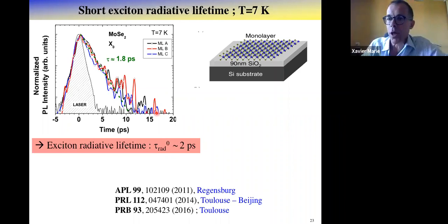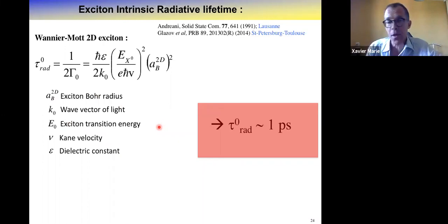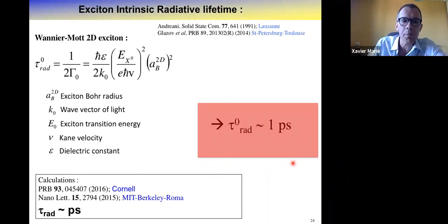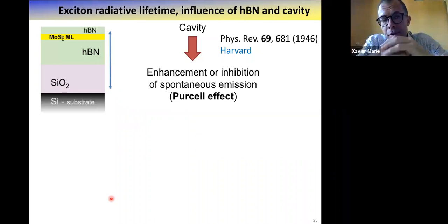So initially you could say, well, this decay is just the fact that you create excitons and very quickly they are captured on defects and you just measure the non-radiative recombination. We were not sure of that, and now we are really confident that this time corresponds to the radiative recombination, for many reasons. The first one, just an indication from the theory, you can estimate the radiative recombination time of your exciton at low temperature when the excitons are in the so-called radiative window. Basically, it scales with the square of the Bohr radius. So with 1 nanometer Bohr radius, you put reasonable parameters, and you get a radiative recombination time at low temperature of the order of 1 picosecond. And more sophisticated calculations indeed confirm this kind of basic calculation.